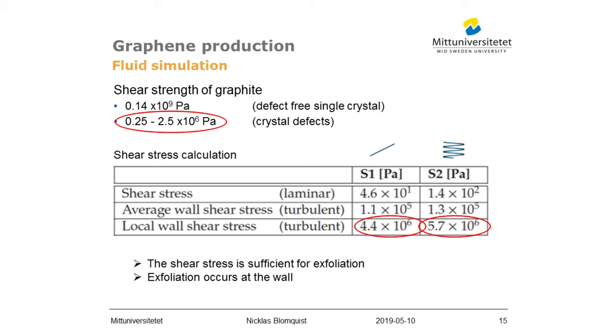Only the local wall shear stress in the system had a high enough shear stress to overcome the shear strength of graphite. And that means that the exfoliation occurs at the tube wall and not in the fluid between these laminar shear layers.